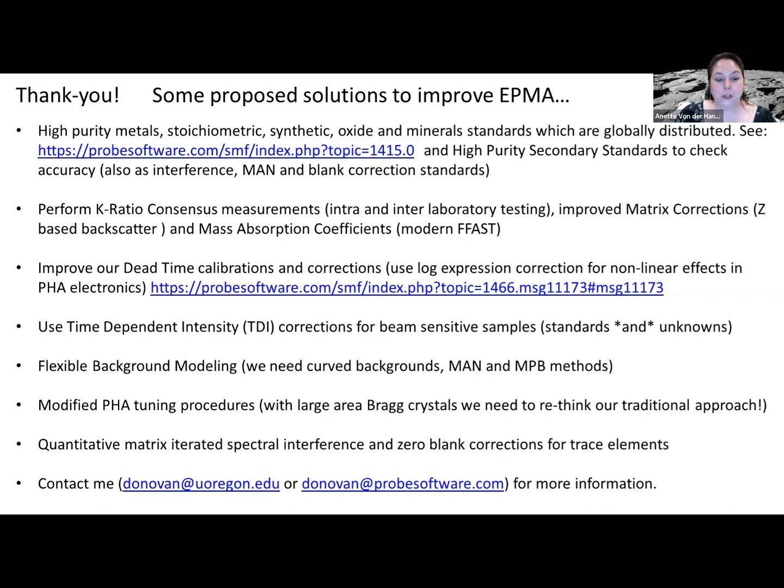And I just really want to point out that if you vet your standards properly, and you know which ones work and which ones don't in your lab, and which ones you might need to replace with something more appropriate, and if you actually do K ratio tests and dead time tests, you can really have an instrument where you can do very advanced techniques while doing very straightforward automated analysis.